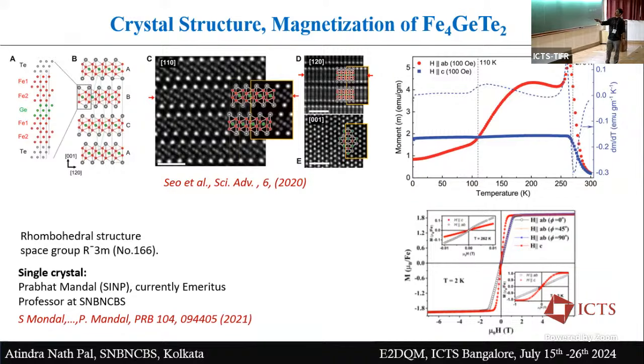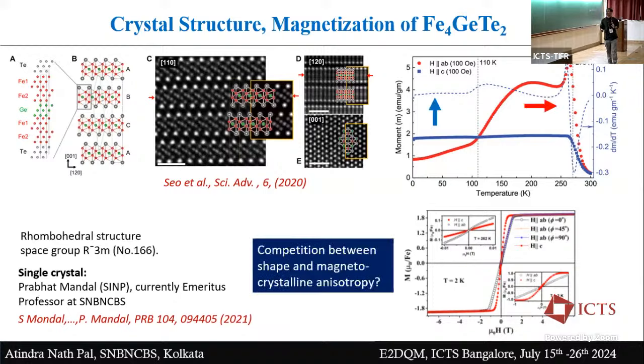This magnetization curve was measured when the magnetic field is in the parallel direction, and this blue curve when the magnetic field is in the Z direction. Now you see after 120 Kelvin it switches. That means there is a change of spin orientation, easy axis orientation, if you go below 120 Kelvin. In literature, this has been described as a spin reorientation transition. In this high temperature limit, the easy axis is in plane, and below 120 Kelvin, the easy axis changes to the C direction. You can see this also in the imaginary curve, which also flips. So that means there is a competition between shape and magnetocrystalline anisotropy as a function of temperature.